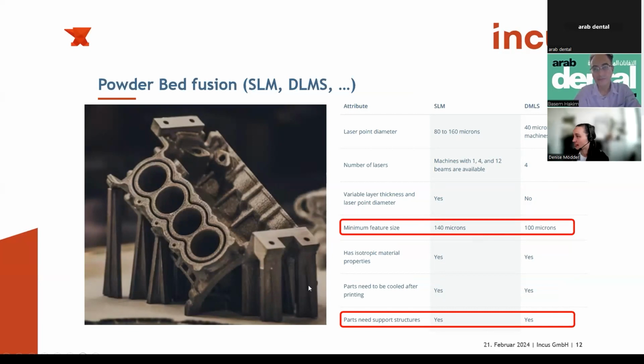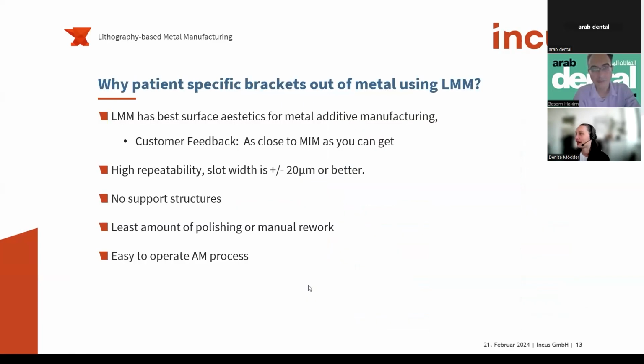In comparison, we have a really great surface aesthetic at the end. We are similar to what people usually know in the metal injection molding industry, with a surface of roughly 2 micron Ra. We have a high repeatability. For example, we measured the slot width of the brackets. We are less than plus minus 20 micron. I mentioned already we don't have support structures, and the polishing or manual rework of the brackets is really minimized.